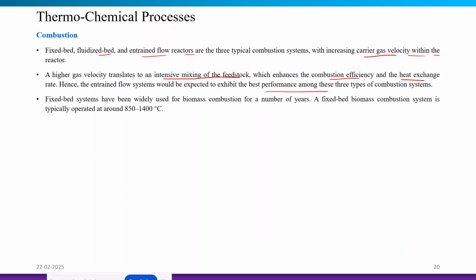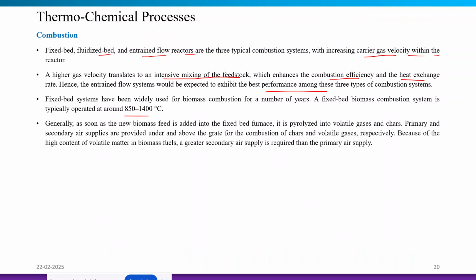Hence, the entrained flow system, out of these three, would be expected to exhibit the best performance as a combustion system. Now, the fixed bed system has been widely used for biomass combustion for years, and a fixed bed biomass combustion system is typically operated at around 850 to 1400 degrees Celsius. Generally, as soon as the new biomass feed is added into the fixed bed furnace, it gets pyrolyzed, and it forms volatile gases and also solid chars.